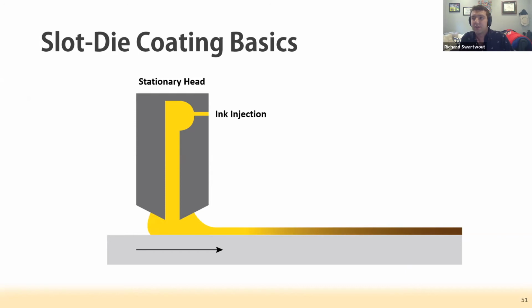We inject ink somewhere into the die. It then flows through the slot down the die's length, injected out the bottom, and then dispensed onto a moving substrate. This is then dried a little bit uncontrollably into the crystallized film of interest.